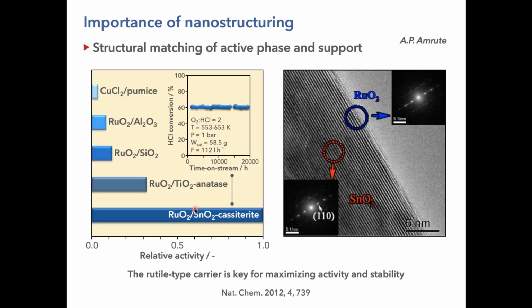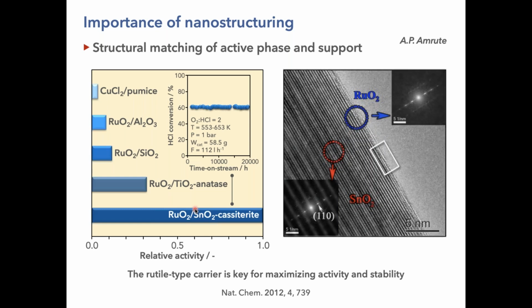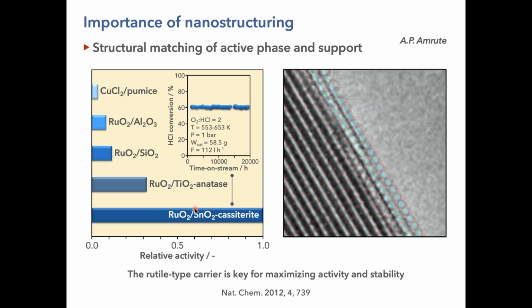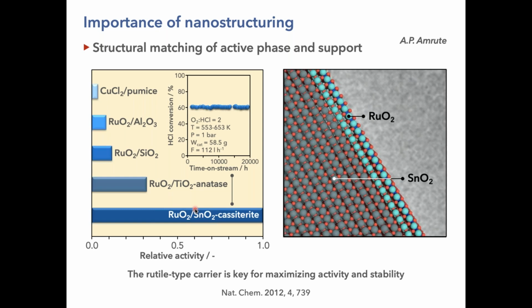Tools like we show over here on the right, aberration corrected microscopy, enable us by zooming to see that actually in the industrial catalyst we have 2 layers of ruthenium oxide epitaxially grown on tin dioxide. And the same active phase, ruthenium oxide, supported on alumina or silica, displaying nanoparticles rather than films, will be as mediocre as the copper chloride catalyst developed by Deacon. So that is an example of how important the nanostructure of a catalyst is.